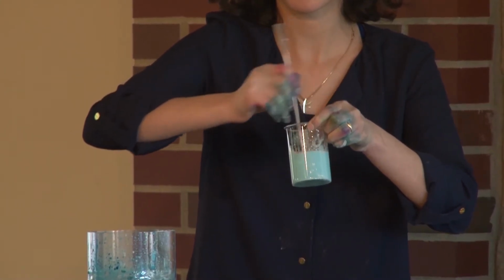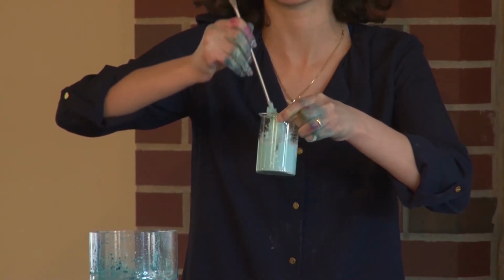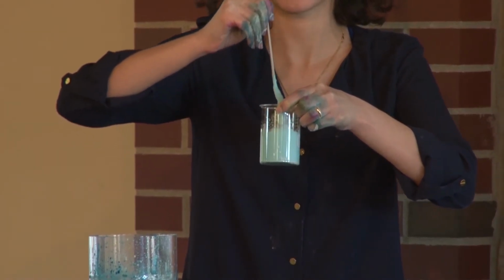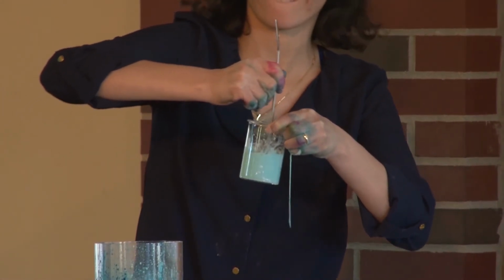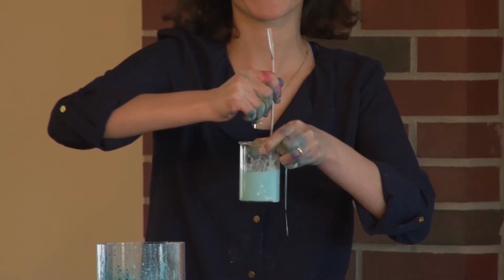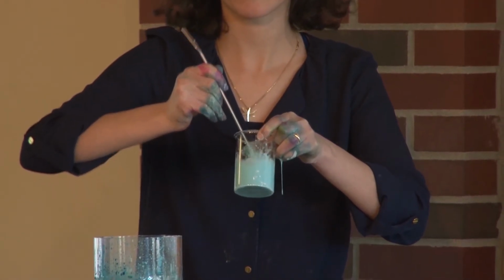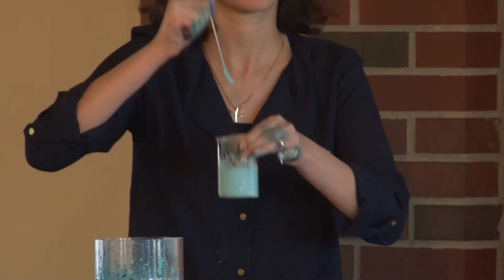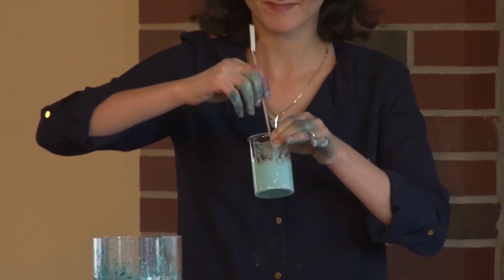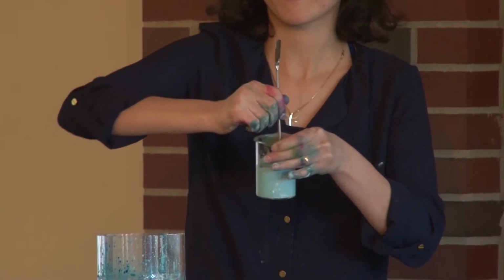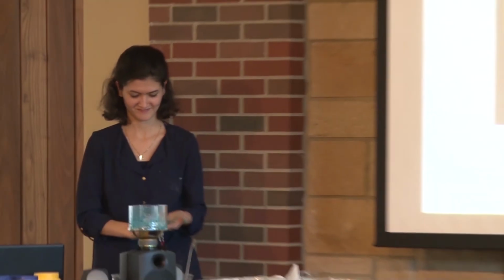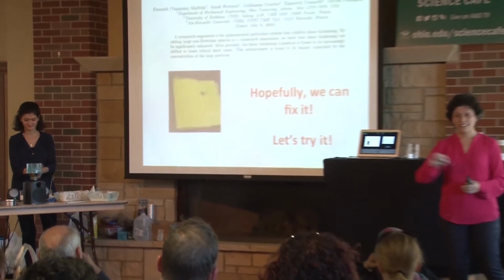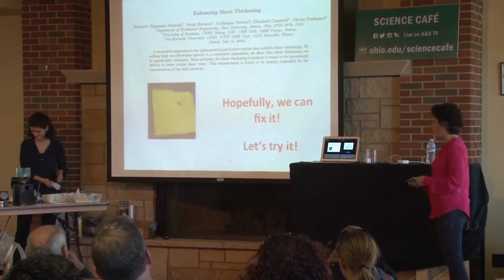If you don't believe us, please come and try it. Polyester particles, and they can be anything. We tried it with PMMA plexiglass particles. We tried it with glass particles, with silver-coated plexiglass particles. We did it with everything, and it worked. Okay. She was able to stir it before. Adding a little bit of large particles enhances the shear thickening a lot.